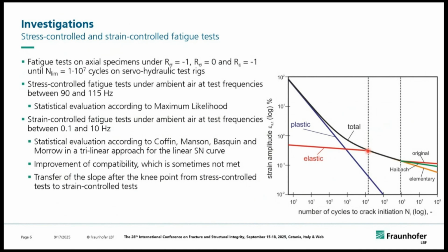fraction of the strain life curve into 3 parts, and especially account for the fact that in the stress-controlled area around 10 to the power 6 cycles we have something like a knee point, which is classically not incorporated in the tests and in the evaluation according to the classic approach from Coffin-Manson and Basquin and Morrow.